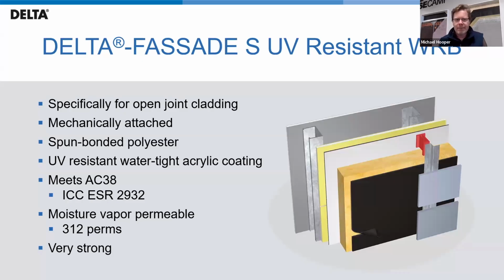We use a spun bonded polyester. The polyester has a much higher tensile strength. Because this is exposed to winds that cladding would typically protect it from, we want that higher tensile strength. The membranes are coated with an acrylic coating that provides the UV resistance. And this will allow for open joints as wide as 2 inches and up to 50% of the overall surface area. And there is no other membrane on the market that allows that level of exposure. It's an incredibly permeable product at 312 perms, which means it's not going to slow down the drying of your assembly at all.